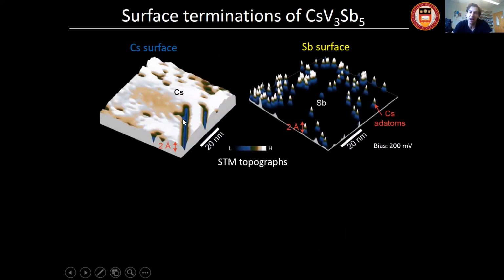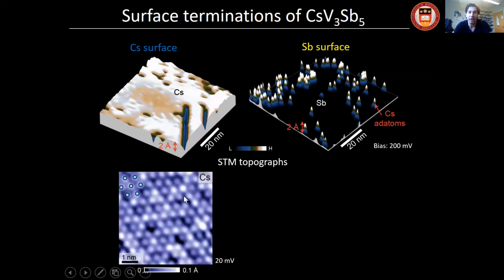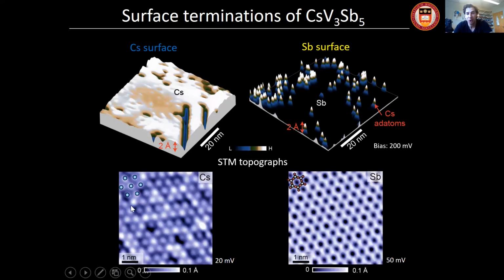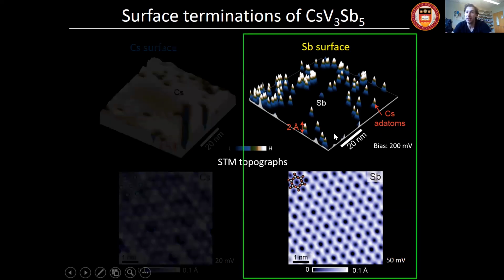And this is the large surface morphology that you can see. If you zoom into smaller areas, you can see the atomic structure. Here's the triangular structure of the cesium layer, and here's the topography of the antimony layer as well. What we found is that even with this low temperature cleave, the cesium layer often reconstructs, so there are a lot of missing atoms. You can even see that based on the pits here. So we really focused on this clean, complete antimony layer in our studies.